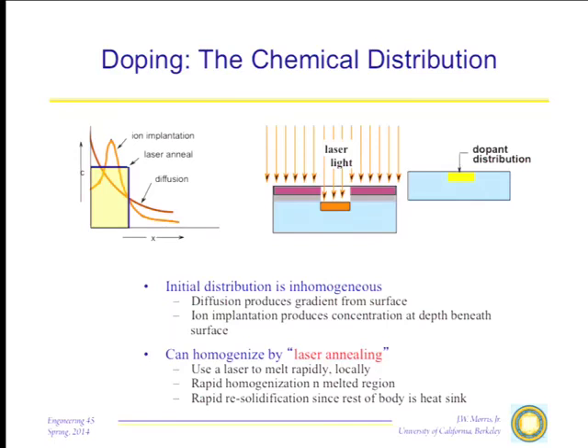Ion implantation has the advantage that depending on the energy of the ions, you get a distribution that looks something like I've shown here, labeled. The ions coming in with a certain controlled momentum will tend to penetrate a certain specific distance into the material before coming to a rest. So you get a profile that actually peaks out slightly below the surface, something like this, and gives you a profile that is a bit flatter than you would get with diffusion, also a bit more concentrated beneath the surface. So this is an improvement.